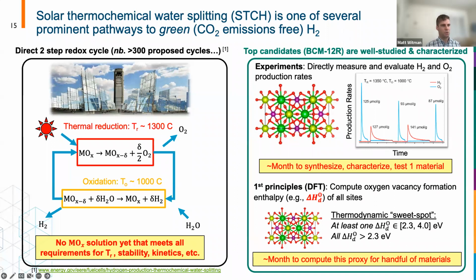And if we compute the oxygen vacancy formation enthalpy of all sites in the crystal structure, we can narrow down whether a candidate should be possible to be used in STCH based on these criteria here, which is basically just saying that all these oxygen vacancy enthalpies should show up in this sweet spot range, and at least one of them should be, and that all of them should be greater than the minimum. But there's different ways you can play around with it, but that's the first level down-selection criteria that it has to meet.